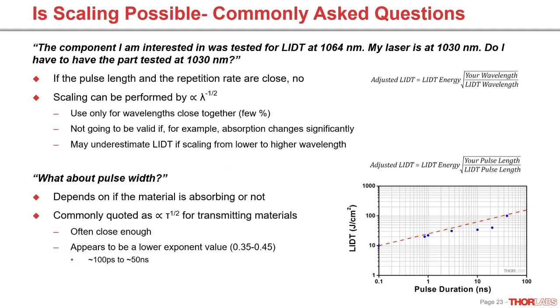And no, you don't necessarily have to have the part tested again if the wavelength is within a few percentage points of our test wavelength, and if the pulse and the repetition rates are relatively close. So you can see how this scaling can be performed there. This isn't valid over any range where the absorption is going to change significantly or where the properties of the materials are going to change significantly. So for example, we have 1064 to 1030 here, and something like that should be valid as long as the material doesn't have a large absorption band at one or the other of those wavelengths, which for most of the materials we're typically using, they don't.